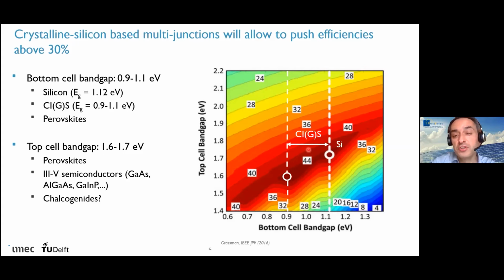And the good news — this is a plot where you see the maximum efficiency you could reach as a function of the bottom cell band gap and the top cell band gap. The good news is that the highest efficiency region is when your bottom cell is between 0.9 to 1.1 eV. And 1.1 eV is actually the band gap of silicon.